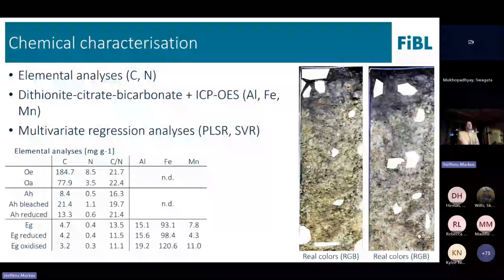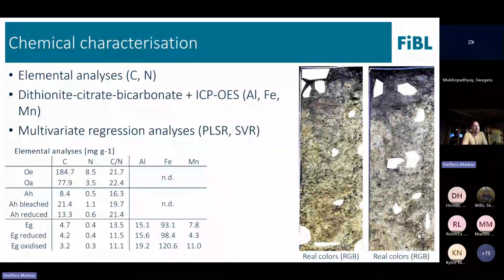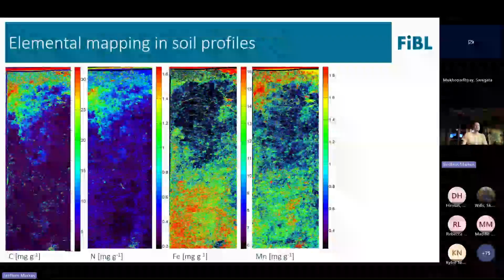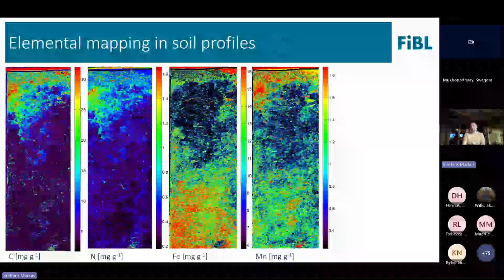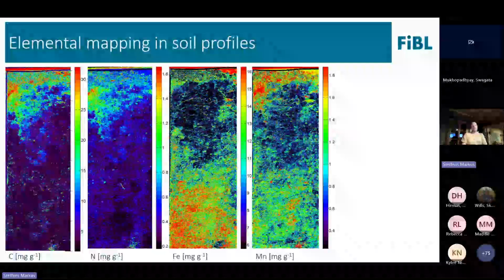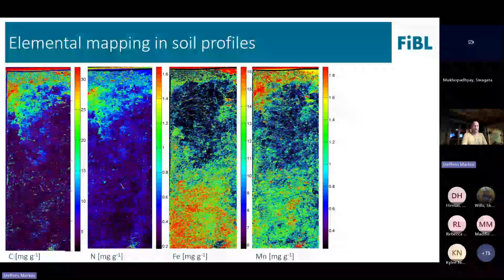And the third step was, of course, we took samples and we did classic analysis. So for carbon, nitrogen, and then for some metals, so aluminum, iron, and manganese. And then you can imagine you can do regression analysis, and then you can make maps, so elemental mapping and soil profiles. And now here you see carbon, nitrogen, iron, and manganese.